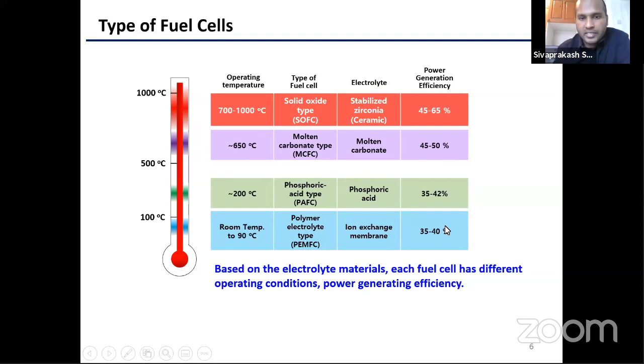Based on the electrolyte materials, we can use different types of fuels for the fuel cells. Among all the fuel cells, stabilized zirconia is an oxide ion conductor, where we can basically use any type of carbon fuels, hydrocarbon fuels, or hydrogen. Whereas in ion exchange membranes, we can only use pure hydrogen, about 99.9% hydrogen as the fuel. But in solid oxide fuel cells, we can use all the carbon or hydrocarbon fuels, even if they contain sulfur or other contaminants.